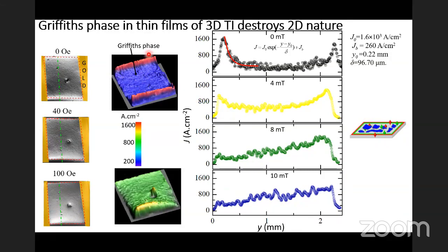So in the bulk of the system you already have these patches of local order, which are surrounded by normal regions of electrons. So the current essentially channels through the edges and doesn't flow through the bulk of the system, and only a very low amount of current flows through the bulk because you don't have a uniform conducting region. So there are these local pockets of order present in a medium of normal electrons, which are generated by disorder. Therefore the current channels through the edges, and as you apply a magnetic field, it causes suppression.